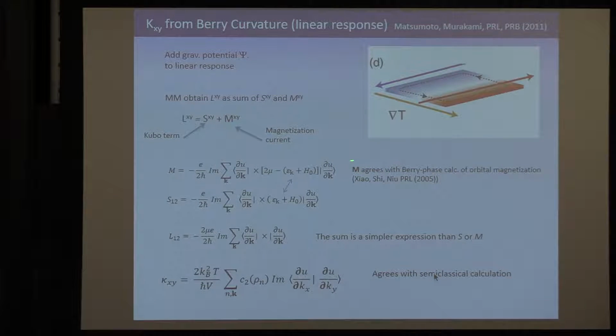And they obtained the orbital magnetization has exactly the form that Murakami derived from the Kubo approach. Okay, but if you add them, the difficult part cancels out, leaving behind a rather simple form, which is exactly what we had obtained, or they had obtained, using the semi-classical equation. So it all works out. Right? So I find this theory to be convincing because you don't have any wiggle room, so to speak.